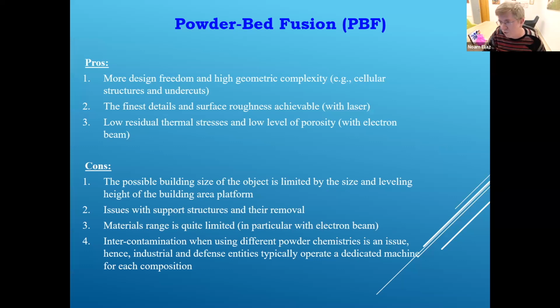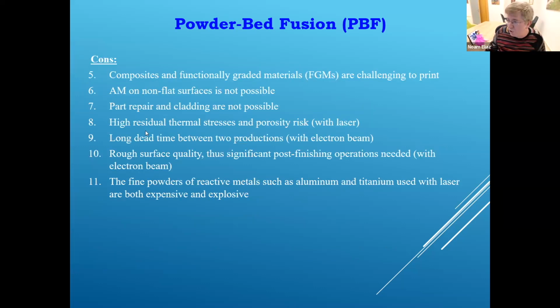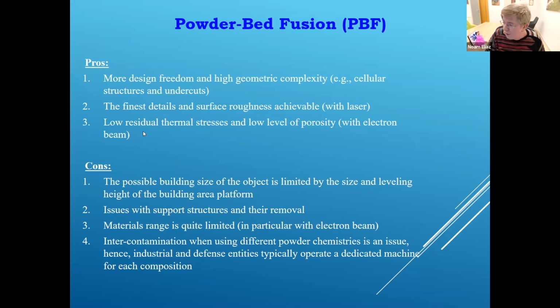It is not trivial to change the materials and the design of the building chambers to adapt for the high temperatures and the aggressive environment. There are issues with the removal of the support. Sometimes it's complicated. The materials range is quite limited, in particular when you work with the electron beam melting technique in vacuum. There you are limited to vacuum compatible materials, for instance, and all the gassing and so on. And intercontamination that people sometimes ignore.